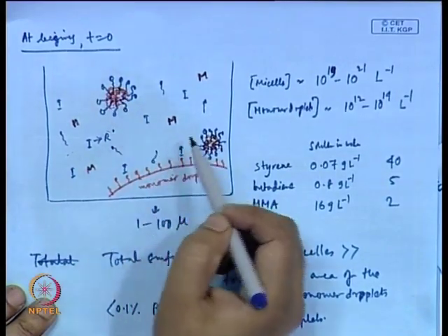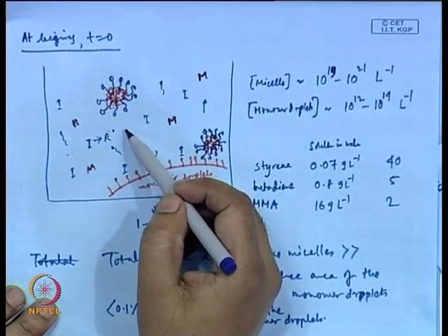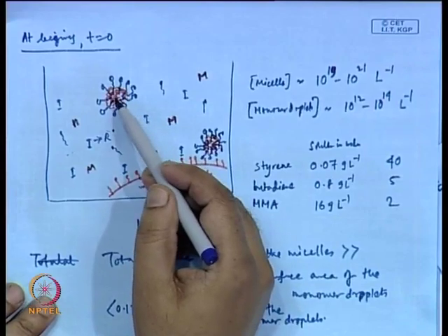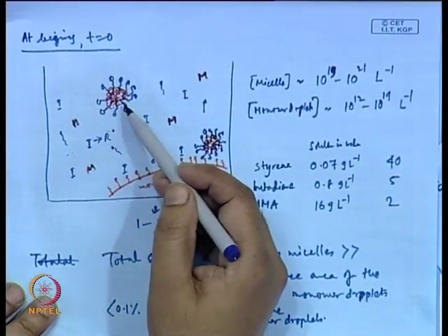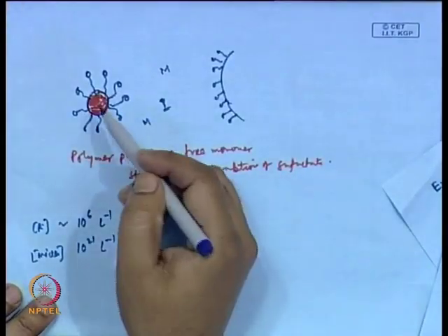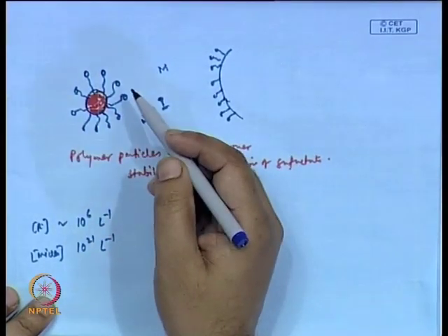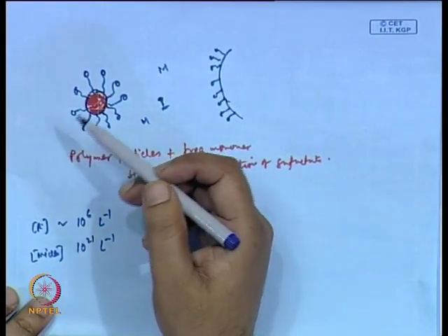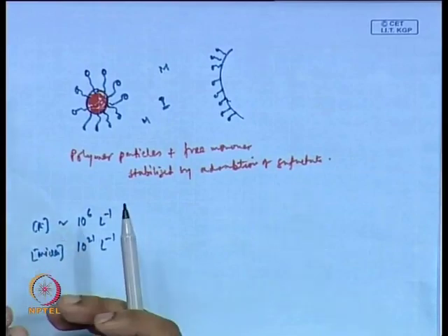Once this R dot, or an oligomeric propagating radical, gets into this, they start polymerization. This polymerization continues till the second radical gets into this reactor, because the size is very small. If the second radical gets in, the effective radical concentration goes high, so immediately the bimolecular termination reaction happens.